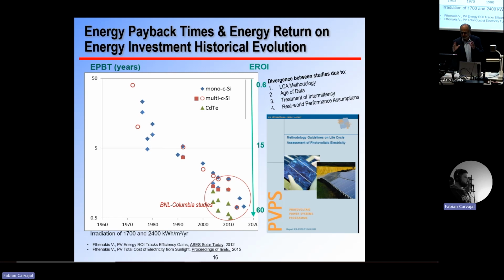Early on, we had inefficient systems, and we were using a lot of cement on the basis. We had 640 micron silicon wafers, not a very good material utilization. Early on, the energy payback time was bad, but by now, and actually perhaps this picture here is 5 years old, the energy payback times can be down to half a year.